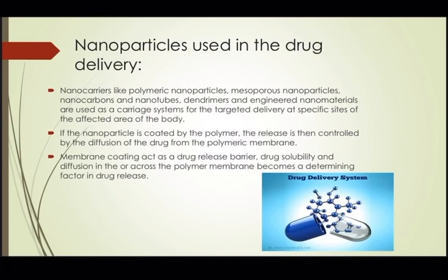Basically, if the nanoparticle is coated by the polymer, the release is then controlled by the diffusion of the drug from the polymeric membrane. Membrane coating acts as a drug release barrier, and drug solubility and diffusion across the polymer membrane become a determining factor in the drug release.